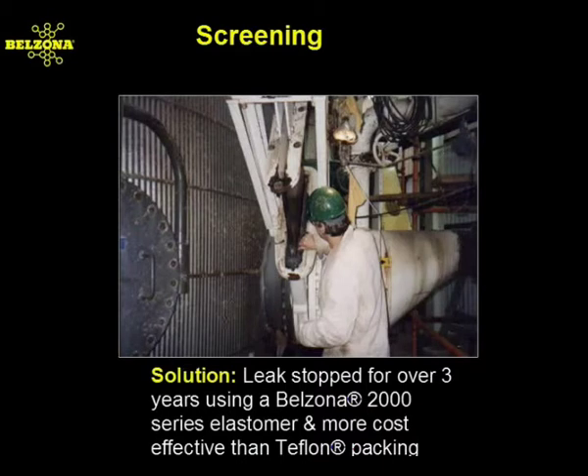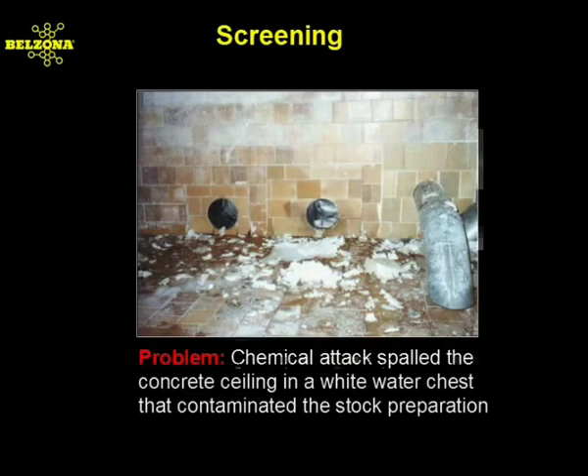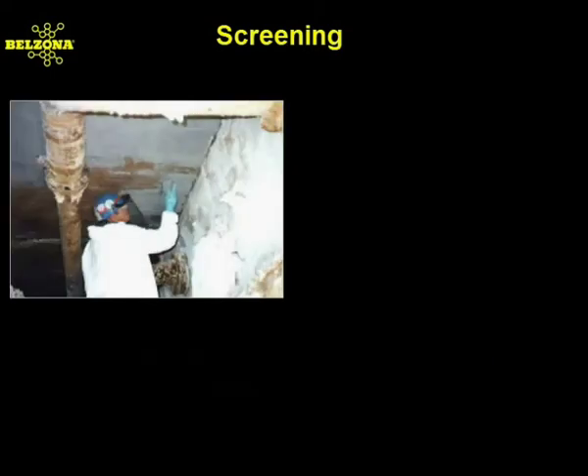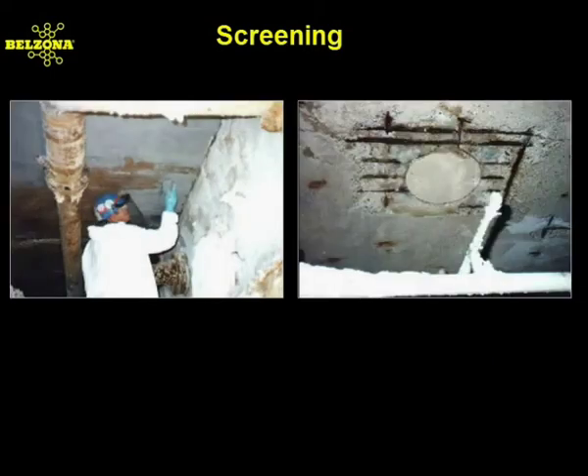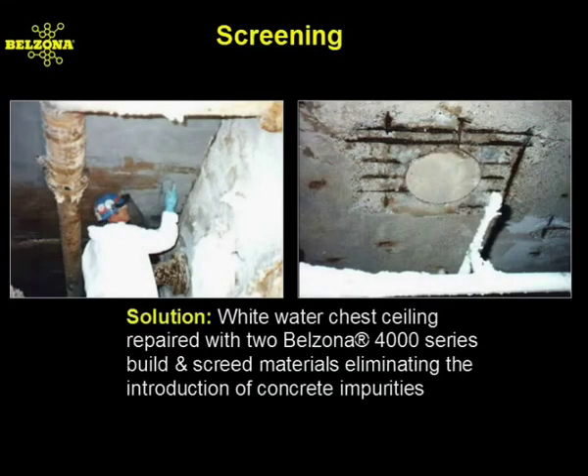In the pulp and paper mills, storage of fiber stock is necessary at appropriate points in the process to provide surge capacity and allow for interruptions in either supply or demand. These chests are usually tile-lined. However, as you can see here, the concrete ceiling has been severely spalled by whitewater chemical attack. In this case, the loose grout and concrete contaminated the stock and caused concerns regarding pulp quality.